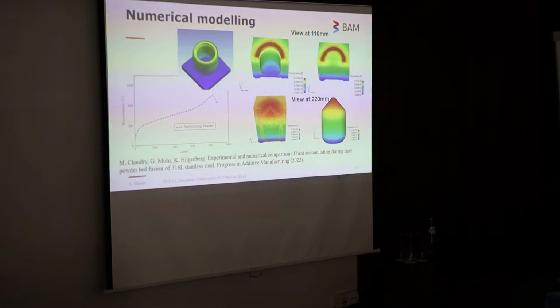Okay, there is another division at BAM working on numerical modeling, and these results are starting from that department. But it's easy to see that the most affected zone in terms of temperature is the cone, because the time between each layer is lower, so the temperature should be higher in the cone region. And we will see some results connected with this fact.